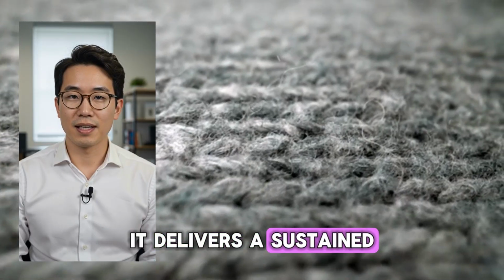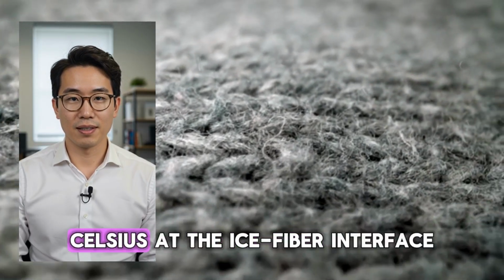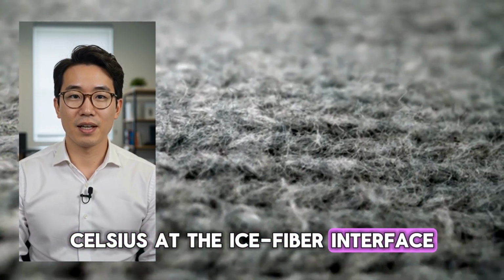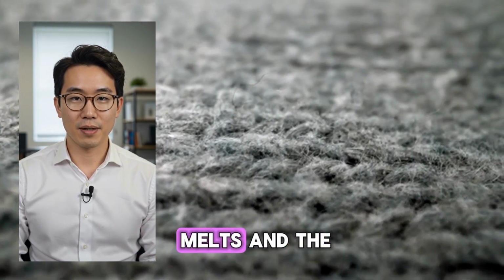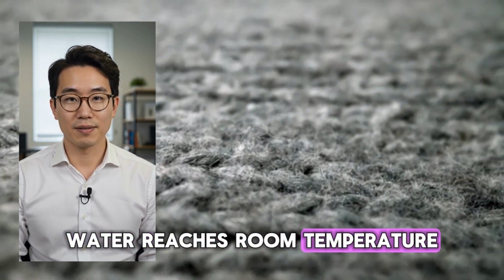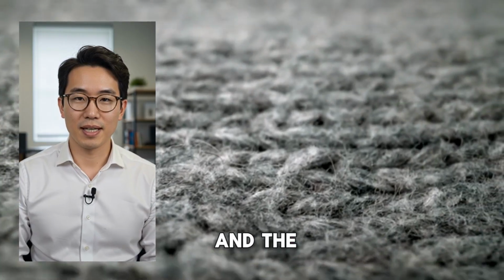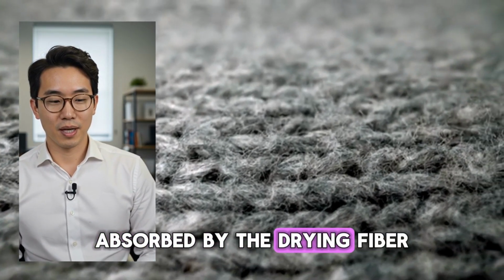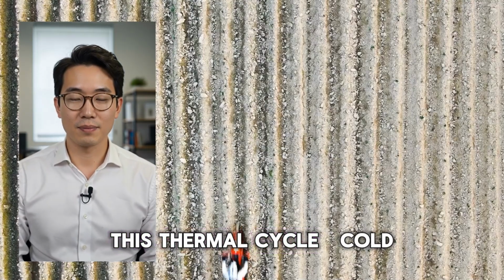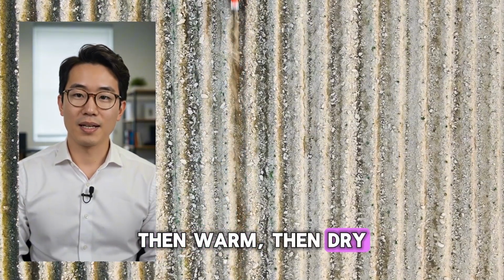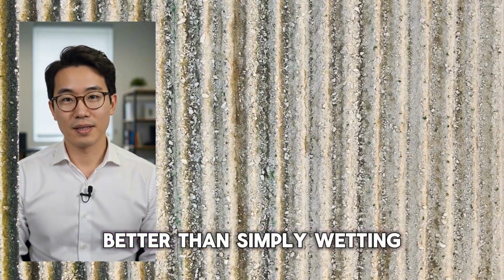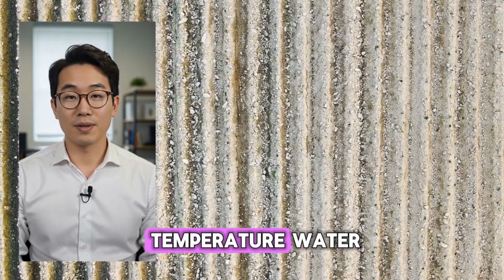It delivers a sustained period of cold, near 0 degrees Celsius at the ice-fiber interface, followed by progressive warming as the ice melts and the water reaches room temperature, then further warming as the water evaporates, and the ambient heat is absorbed by the drying fiber. This thermal cycle, cold, then warm, then dry, is the key to why the ice method works better than simply wetting the fiber with room temperature water.